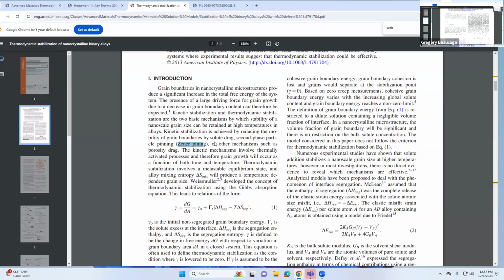So if you have these things like Zener pinning, so those are kinetic solute drag, porosity drag. So if you put pores in, the same thing happens. So basically you can somehow slow down the grain growth. So you start out, the grains would grow from nucleation site, then they grow. You want to get them to be less than 500 nanometers, less than a half a micron, in order to get these effects like Hall-Petch to get a huge yield strength.